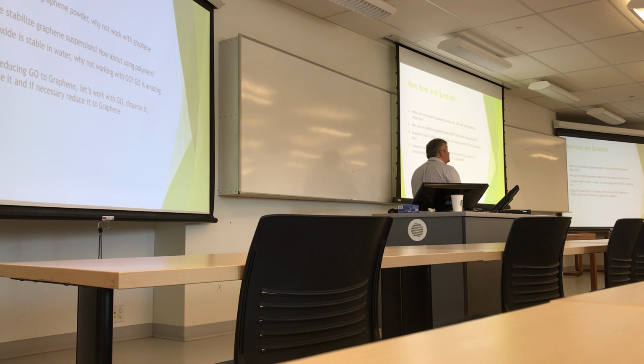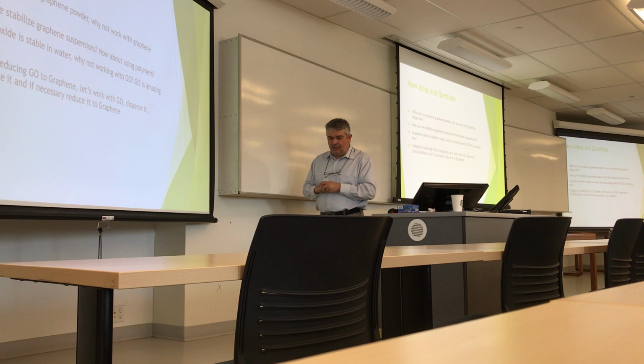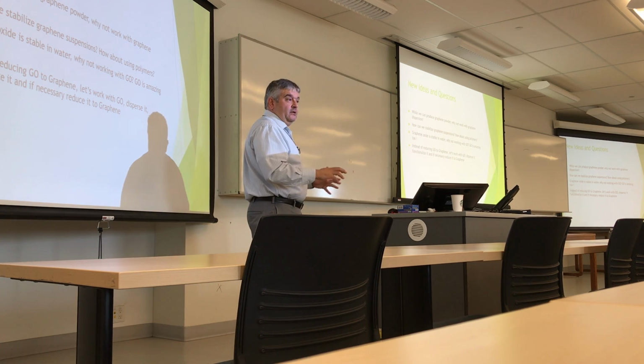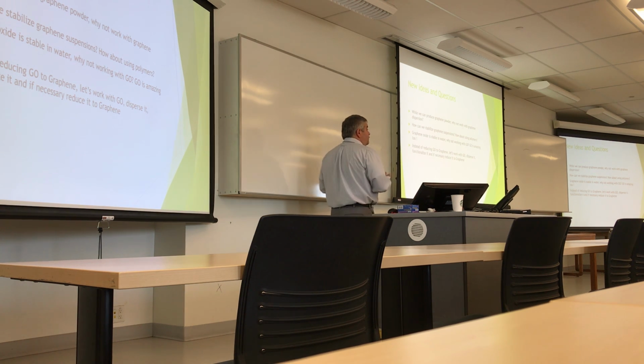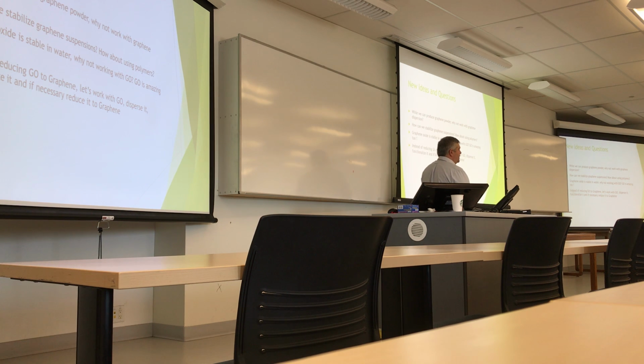And one thing that was really interesting, and one of the major points that we faced, was that apart from graphene, graphene-oxide is stable in water, so why not work with GO? GO is amazing too. That was a very interesting point because everybody was focused on graphene because of the conductivity, but when we were working with the polymers, the purpose was mechanical enhancement, so conductivity was not that much of an issue. And GO was much better to work with than graphene. So instead of reducing GO to graphene, let's work with GO, disperse it, functionalize it, and if necessary, reduce it to graphene.